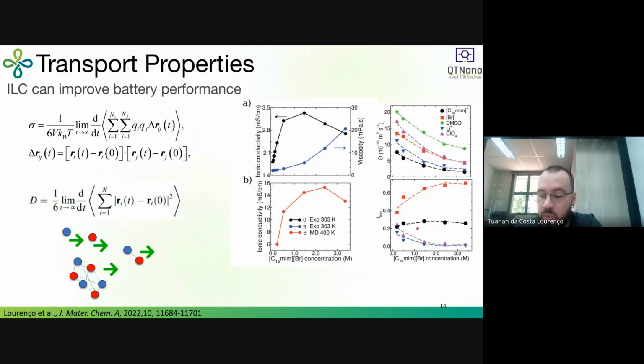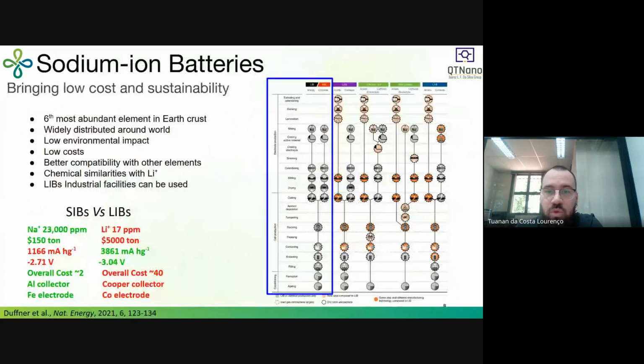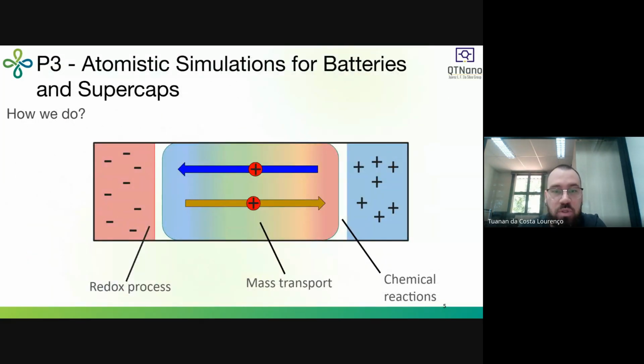When you look at the battery, although we use ionic conductivity as a descriptor of the electrolyte performance, you are not only looking at the ionic conductivity. What we are looking at is the movement of the active metal ion. In a sodium ion battery, say you have a very good ionic liquid with a very high ionic conductivity, but you add just a small amount of sodium. For the battery, this is not good because you don't have much sodium to go from one side to the other.